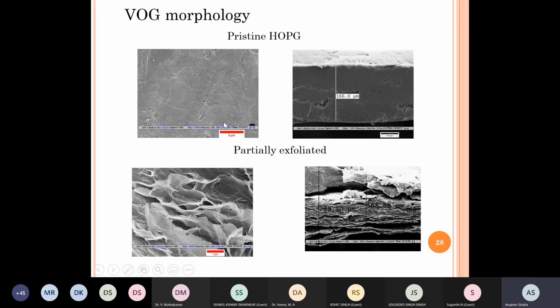When we did exfoliation, partial exfoliation, the top surface, so the bottom two figures, the left hand side is the top surface of the same material. So what is there on the top here, this is what happens after exfoliation, and one can see these graphene nanoflakes which have come out of the surface in vertical orientation.